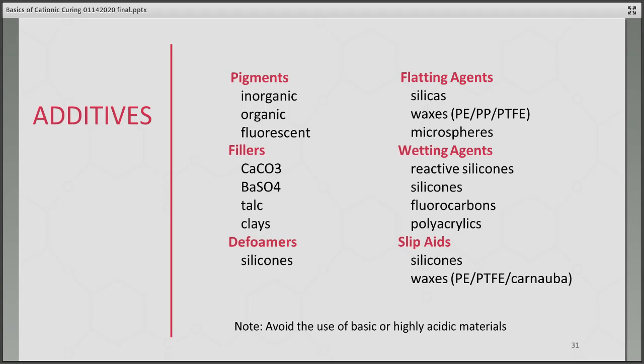Another component of UV curable cationic systems are the additives. I mentioned earlier pigments, so your coloring, you'll definitely use these in inks, but it could be in coatings. You may use fillers, defoamers, flattening agents. One of the properties of cycloaliphatic epoxides, especially CAE, is they give a great looking gloss coating. But if you don't want a gloss coating, you would probably want to add either some silicas or waxes or microspheres into your formulation. You may need wetting agents to wet out on your substrate or slip aids.